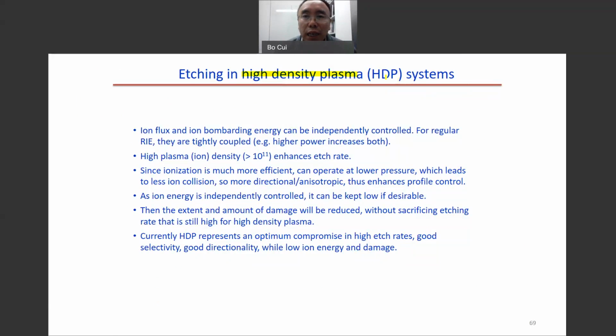High density plasma is called HDP. So we know that for the regular RIE, the ion flux and ion energy are coupled. So if we have higher power, you have more ions to bombard the surface, and you have higher energy of the ions. But for the HDP system, the ion flux and ion bombardment energy can be controlled independently. And for the HDP, we have higher ion density. The ion density is similar to the electron density.